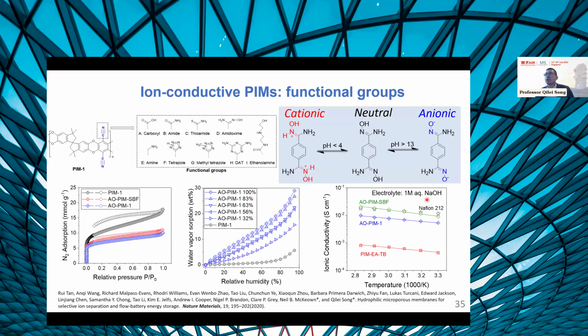Firstly, we demonstrated the amidoxime functionalized PIM. This is a really interesting functional group that can be protonated at a low pH and also deprotonated at a high pH. A very exciting discovery was that we were planning to use this material in alkaline aqueous redox flow batteries. That means in the high pH electrolyte, these amidoxime groups can be deprotonated, and they become ion conductive.